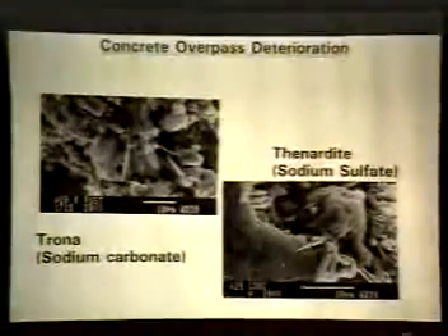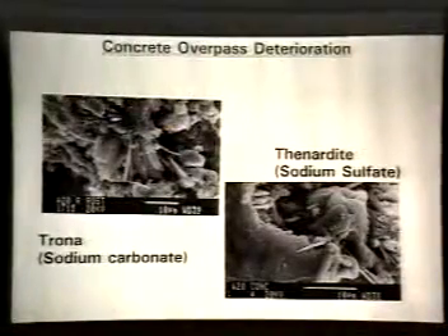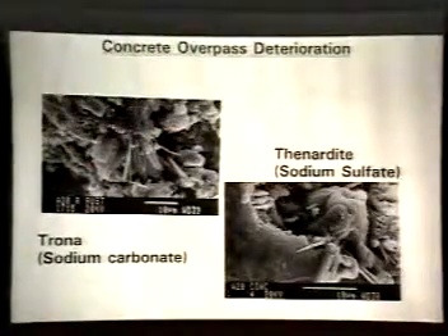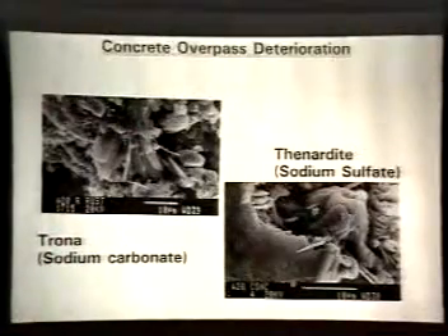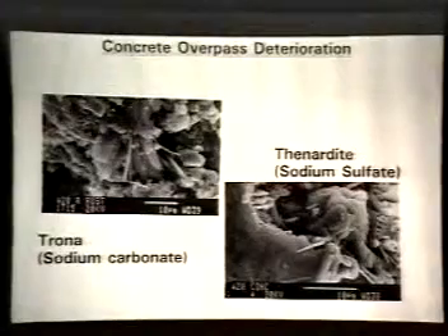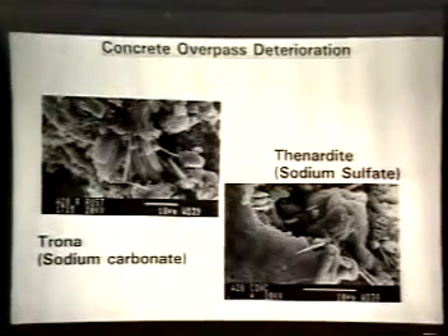Next, please. When we examined the concrete, we found salts, sulfate salts, trona, sodium carbonate, bicarbonate, and sodium sulfate salts up to the rebar level. Beyond the rebar level, the concrete was pretty sound. And we found tremendous corrosion at the paste aggregate interface. This is the corrosion product that we see. Next, please. This is when the repair of the bridge deck was going on, repair only up to the rebar level. And this next one shows the repair of the column structure.